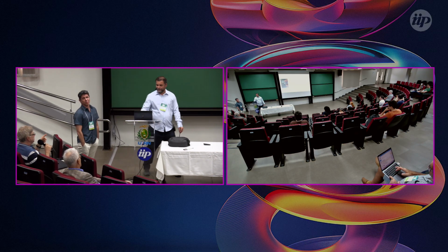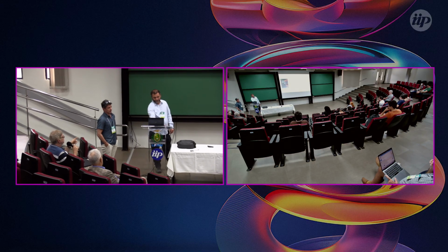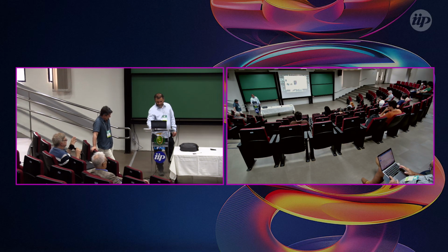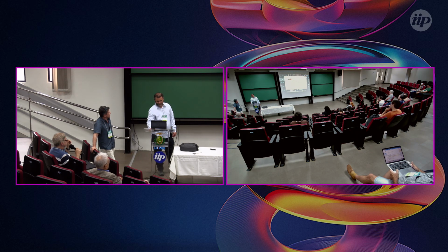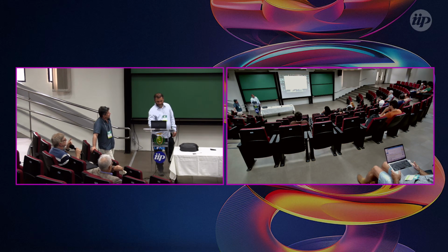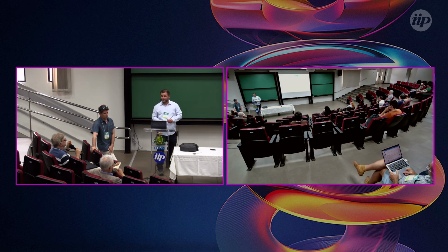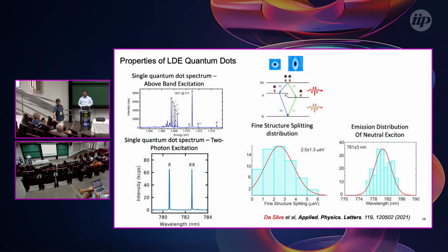In one of your previous slides, you mentioned that to avoid some charged excitons, you excite with 2 photons. Yes. So you have a lot of charged excitons, and then when you excite with 2 photons, you have only neutral exciton and biexciton. So the first thing is, this is a gallium arsenide sample? Yes. So this gallium arsenide is a direct band gap.